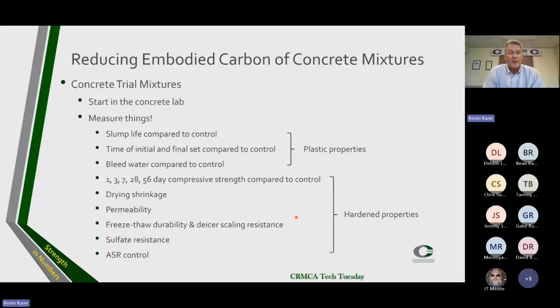When we did the Ocean Journey Aquarium back in 1996 or 97, that was a very challenging 6,000 PSI mix with, at that time, the only high-range water reducer available being an old naphthalene formaldehyde sulfonate. And its effect on that concrete mix was it was very retarded. And I measured it, 16 hours, 16-hour initial set times. I sat there and measured those well into the night, well into the early morning. But I was able to go to Hensel Phelps and say, oh yeah, about this mix you're going to be building this aquarium with, you really need to know this. It's painfully slow to set. And they weren't happy. But it gave them a clue on how they were going to time their forming.